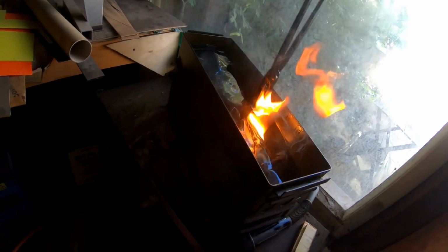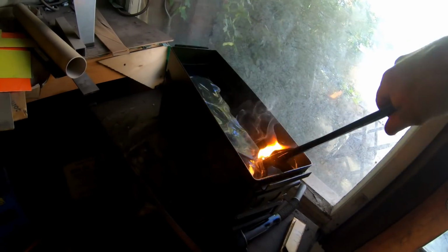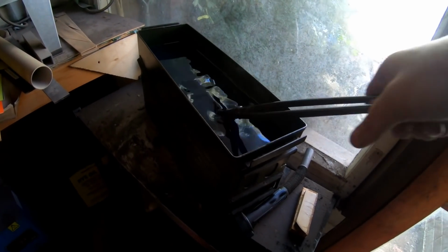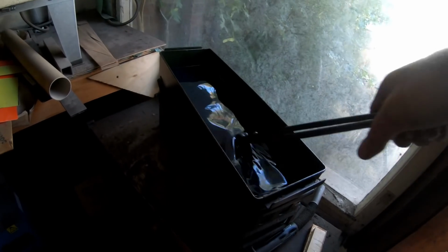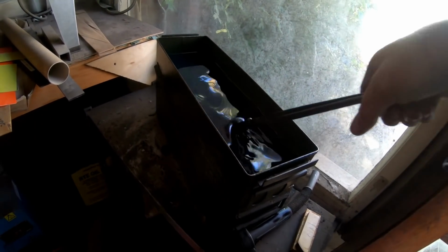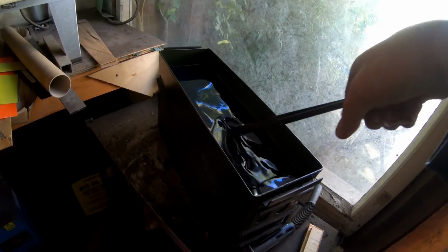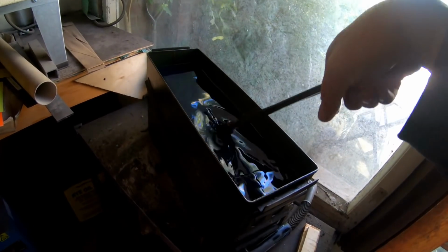It's really important to get that slicing motion. Because when the hot blade first goes into the oil, into the quenchant, it forms a vapour barrier around the blade. The vapour barrier is basically an insulator, and it stops the oil from cooling the blade. So by moving your blade backwards and forwards, especially when it's red hot going into the oil, you disrupt that vapour barrier and allow the oil to have access to the steel and thus cool it in the correct manner. You've got to drop it at the right temperature rate to affect full hardness. The oil I'm using is a special O1 quenchant. It's designed for O1 tool steel. It drops it at the right rate.